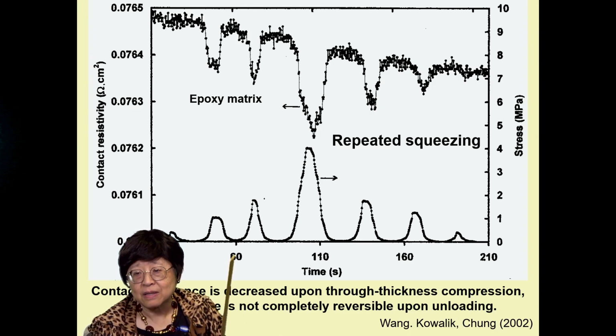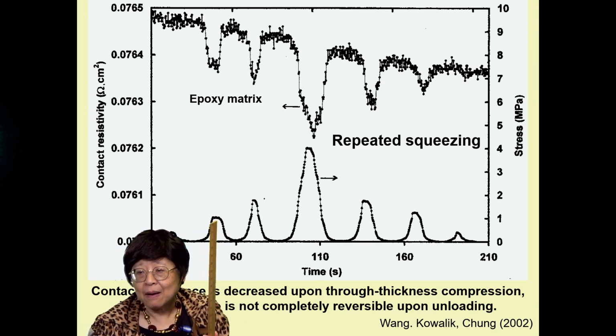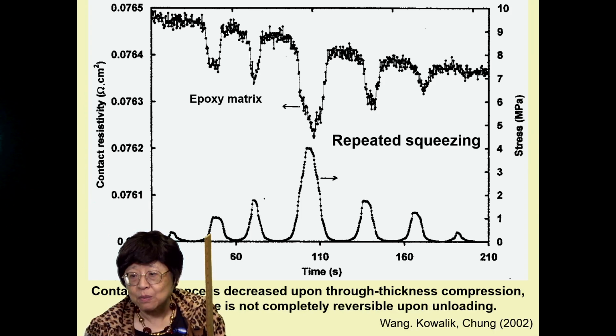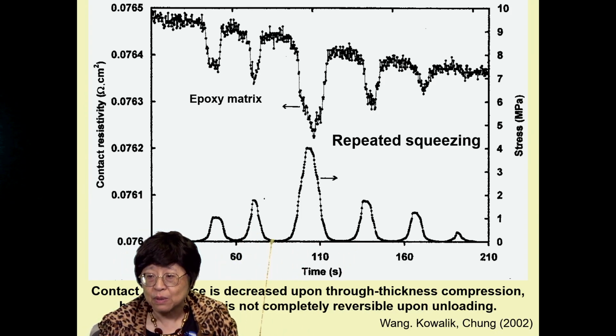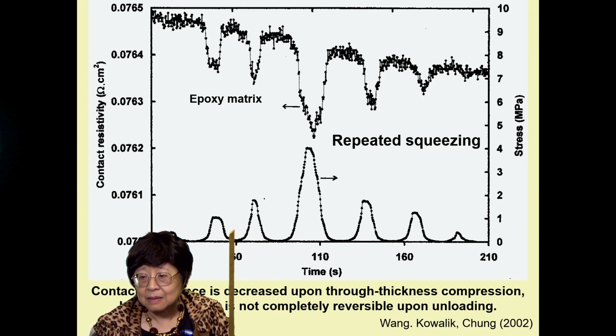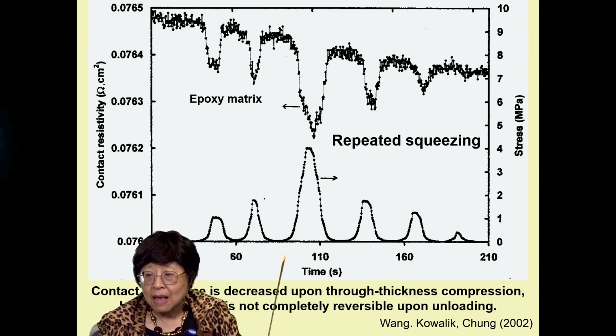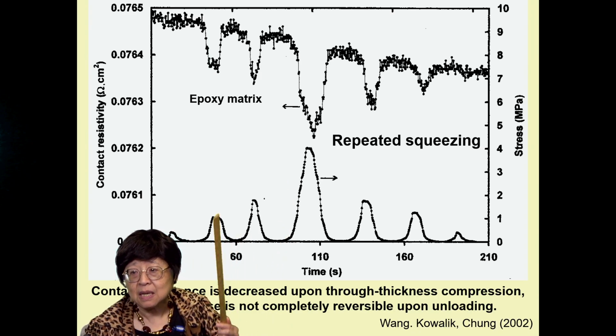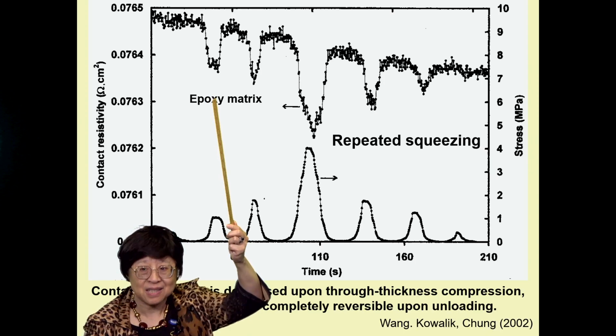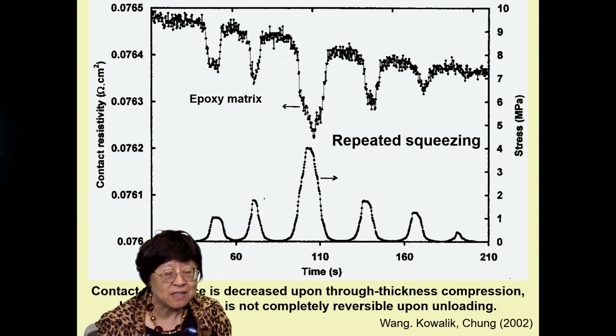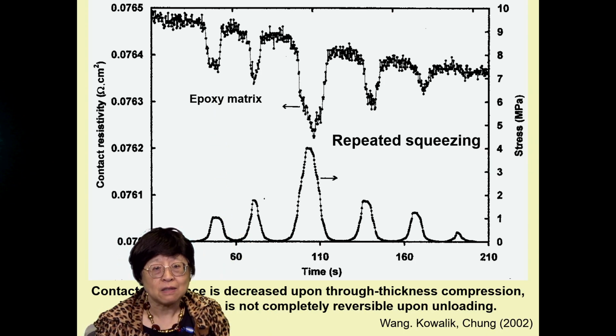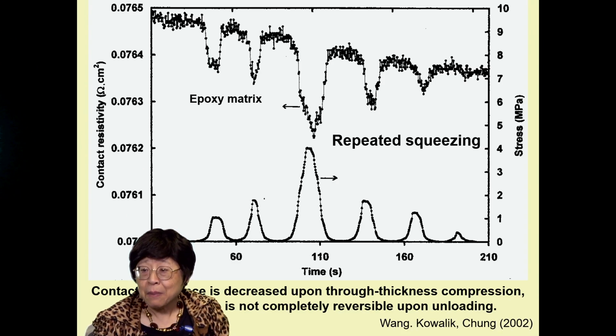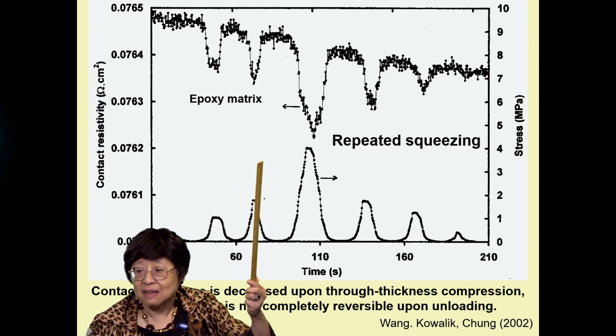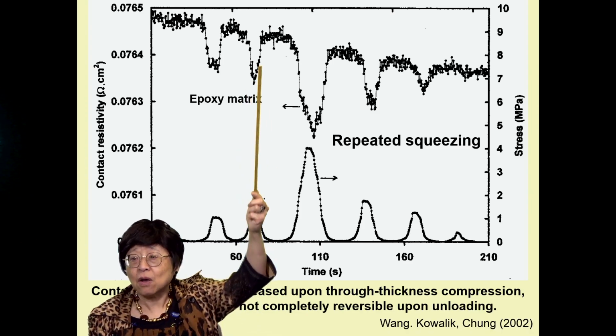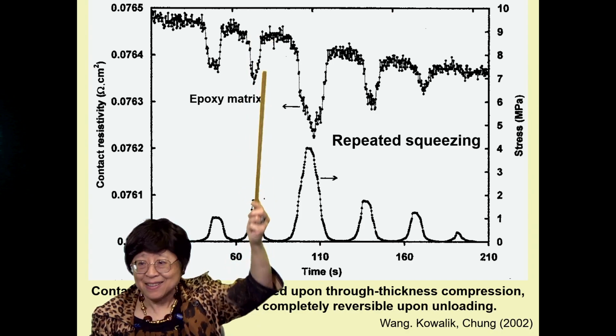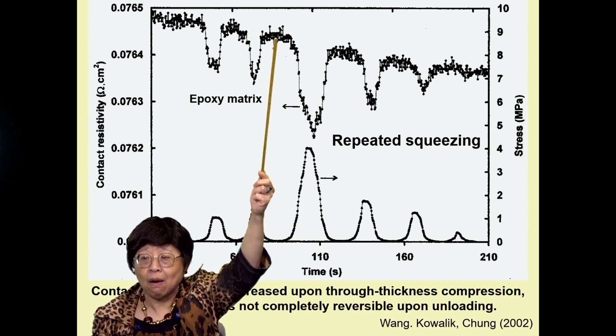And so we measured this contact resistance during the squeezing, a number of cycles of squeezing at different maximum loads. And we find that every time we squeeze, the contact resistance decreases. That's because the chance of fiber-fiber contact across that interface is increased. But very interestingly, the resistance doesn't go all the way back. You squeeze and unload, it doesn't go all the way back.